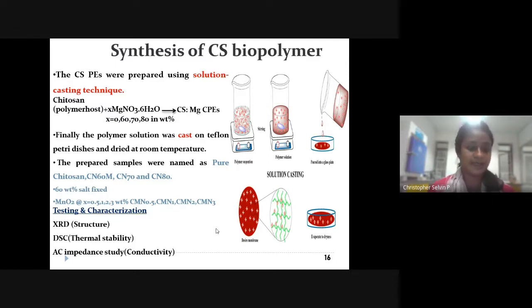The samples are named as pure chitosan, that is chitosan with 0 weight percentage of salt, and chitosan with 60, 70, 80 weight percentage of the salt. Here we have fixed 60 weight percentage of the salt to prepare the composite polymer electrolyte using MnO2 filler, and this salt concentration has been fixed using the ionic conductivity value obtained from AC impedance analysis.